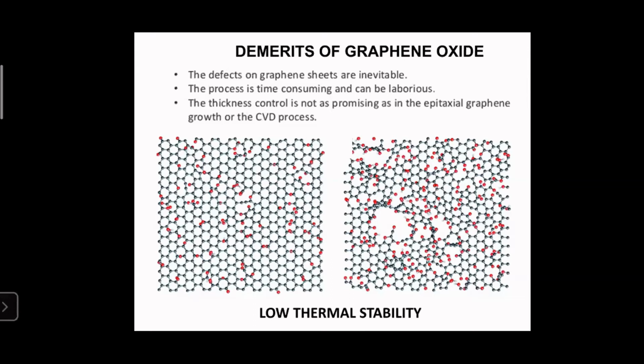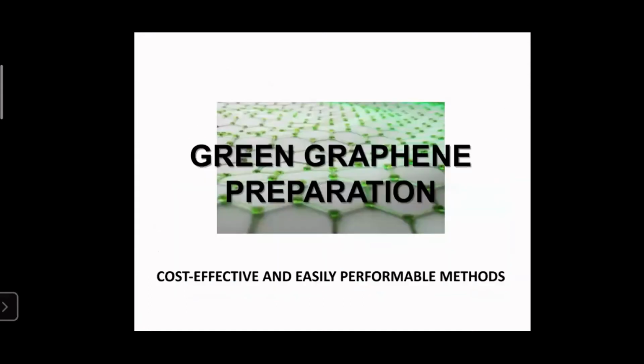It decomposes at about 200 degrees Celsius, and thus graphene derived from graphene oxide cannot be used for high temperature applications. For example, it cannot be used for the conversion of plastics to fuels, for cracking reactions, etc. So we prefer the production of graphene via some green methods. But these green methods should be cost-effective and easily performable.